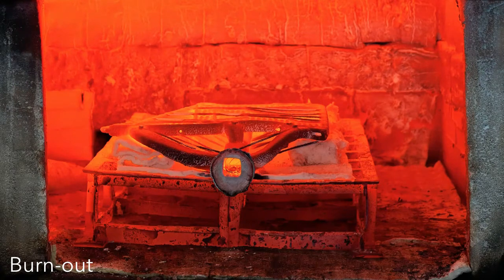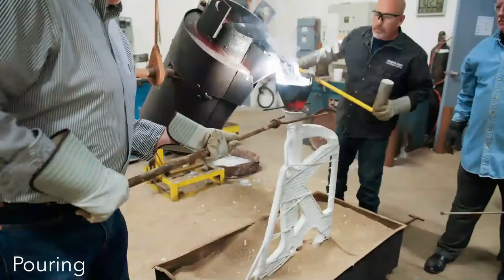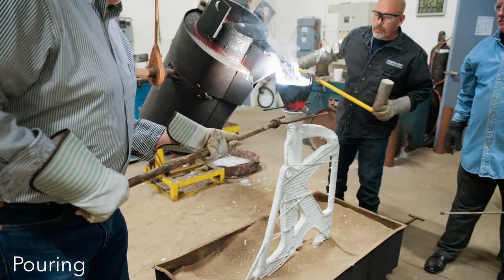After the shell has been burned out, inspected, and cleaned to remove any residual ash, it is then heated up again. And then they first flood the shell with argon, because we're working with magnesium, which is a relatively reactive metal. And you can actually see it flaring a little bit at the top as it comes into contact with some oxygen. It's got an inert gas flux coating in the ladle there. But they're filling up the shell here.